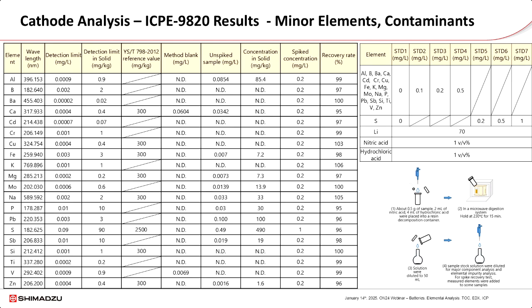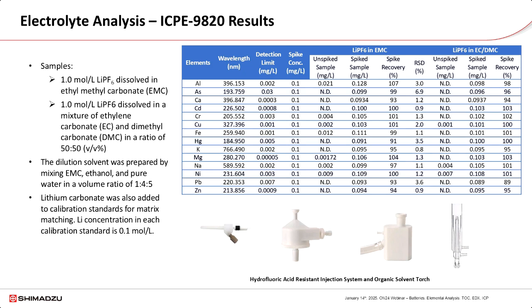Critical here are the spike recovery rate that's in the range of 95 to 106%, as shown in the last column of the table on the left, demonstrating the accuracy of this analytical protocol. Detection limits are also calculated as shown in the third column of the table. As you can see, many of the elements have a detection limit lower than 1 ppb, demonstrating the low detection limit and great sensitivity of this instrument. Also shown here is the digestion and sample preparation technique in the lower right figure, which is unique for this matrix. The last data set shows analysis of electrolyte of lithium-ion secondary batteries.